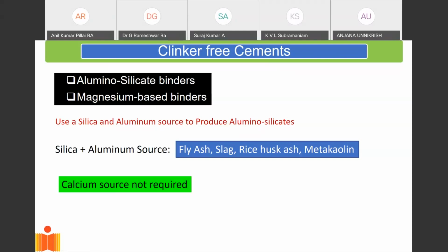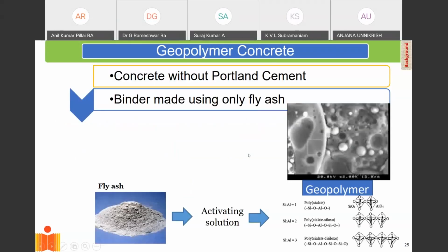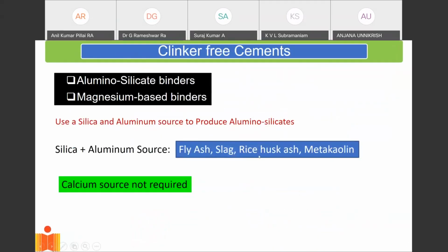And basically, fly ash contains both of these. Therefore, I should be able to make these cements using only fly ash. And we also have other waste materials like slag, rice husk ash, what we get by burning rice husk, metakaolin. These are all essentially waste materials, which can be used as a source for making cement without the requirement of clinker. So this is alternate chemistry, which is at work here.